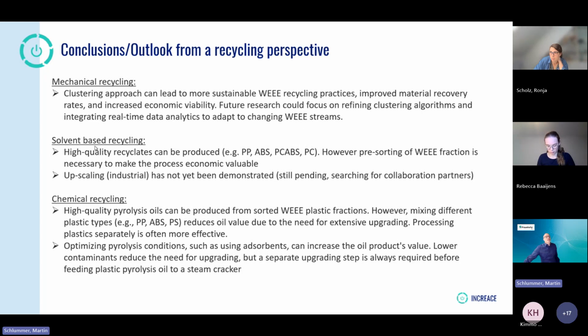For solvent-based recycling, we have found quite nice recyclate qualities for polypropylene, ABS, and PC. However, we sometimes had the issue of pre-sorting the WEEE fractions to reach something like 70% feedstock purity. The upscaling to industrial scale has not been demonstrated so far. This is still pending, and here we are looking for collaboration partners.